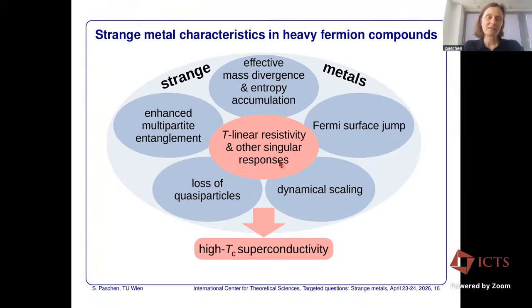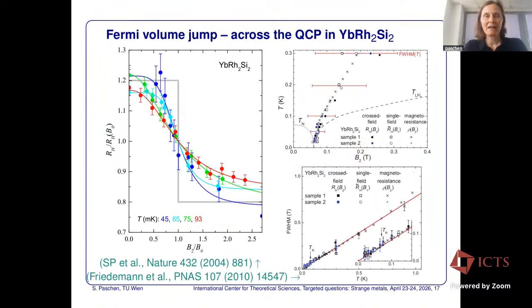So in addition to this linear resistivity that goes along also with other non-Fermi liquid responses in specific heat, thermopower, many different properties, if you look at the Fermi liquid that is adjacent to the strange metal, we see these enhanced or diverging effective masses associated with entropy accumulation, as I already showed to you. We have a Fermi surface jump across the quantum critical point. We have dynamical scaling in different properties. We have a loss of quasi-particles and enhanced multipartite entanglement, and probably many more that are not on my radar. And all of that usually leads to high temperature superconductivity out of that strange metal state.